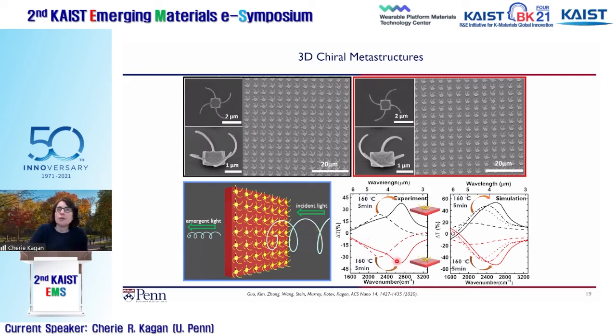So what you can see here is that we made these two different enantiomers. And as you have these structures on a surface, these two are similar in size, but opposite in handedness. And so if you look at the difference in transmission between right and left-hand circularly polarized light, they have very similar magnitudes. I'll focus on the ones after annealing in black and in red. And they're at very similar energies because they have the same lengths of arms, but they're opposite in their sign. And that's simply a measure of the fact that there are two different enantiomers.